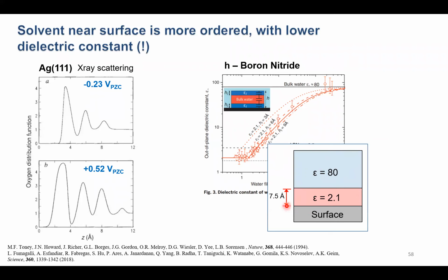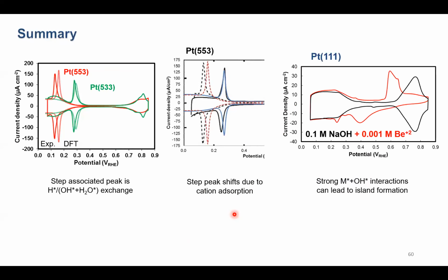And it's interesting that this length scale corresponds very nicely with where we see this ordered water on an actual electrode surface in situ. And so again, we don't know what the dielectric constant of water is next to a platinum electrode, next to a silver electrode, but I think there's lots of evidence to say it is much, much lower than what it is for bulk water. And so we really need to think about how the structure, the dynamics, and the dielectric properties of water are different near a surface relative to that of bulk electrolyte.